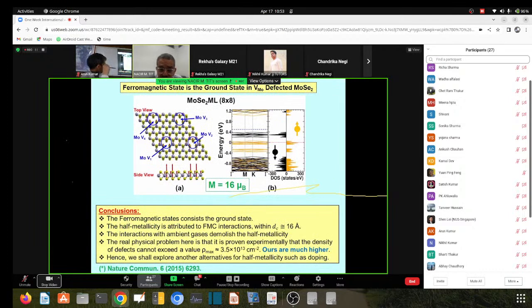Then I should move on because I described everything basically. Also the critical length for the existence of ferromagnetic interaction is shown to be about 16 angstrom. Moreover, we also tested a sample where we took the 4x4 and replicated it in a sample of 8x8. So it contains 4 vacancies of molybdenum, and we studied the band structure, total density, total energy, and magnetization. It's about 16, which is about 4 times the magnetization of the 4x4 sample. Therefore, we are proving that there is ferromagnetic interaction where all the magnetic moments add up to 4 times.